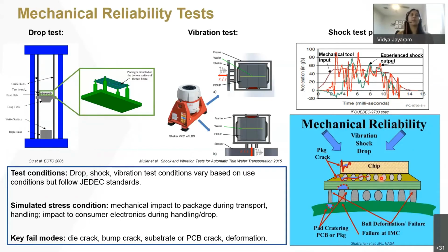So we covered some of the accelerated stress testing. And then you also have mechanical reliability tests to simulate the package being dropped or experiencing some kind of vibration or shock. And we typically follow JEDEC standards to perform this kind of testing. The stress condition that it would most simulate would be transportation, handling, and even end use where the consumer handles the product and it experiences drop and shock, etc. And as we covered earlier, this would be more brittle types of failure modes. You would see die crack, bump crack, substrate or PCB crack, deformation, etc. These are things you would be able to detect with the mechanical reliability test.